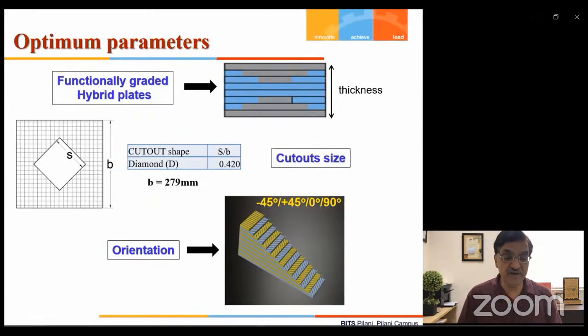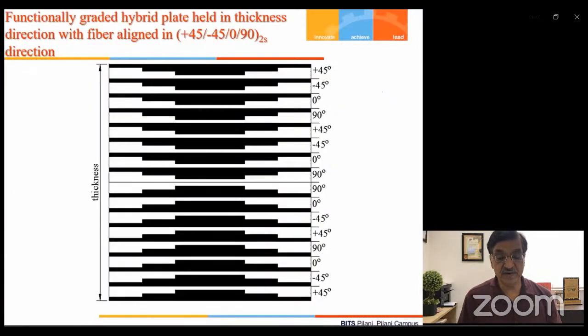In this particular presentation, we are presenting the post-buckling strength under combined in-plane shear and uniaxial compression. Here we are taking the diamond shape cutout with the large size. Three sizes of diamond shape cutouts have been considered: small, medium, and large. This represents the functional gradation of the laminated composite material for -45, +45, 0, and 90 degree orientations, taking 5 plies in each layer for each functionally graded laminate.